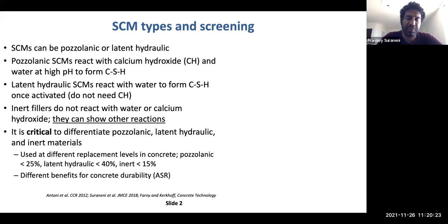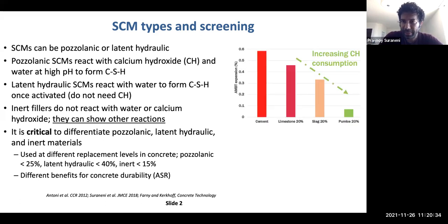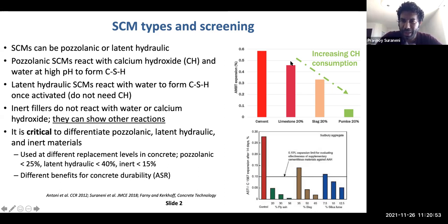It's also critical to differentiate these different materials because they have very, very different benefits for concrete durability. I will give an example with alkali silica reaction. So if you look at pumice, which is a very reactive material compared to limestone, at 20% pumice, if you look at expansion in the ASR test, it is about 8 to 10 times lower than the expansion that you get with limestone. Similarly, if you look at the replacement levels needed to mitigate alkali silica reaction, with silica fume, you can actually mitigate it with just about 8%. For fly ash, you need about 20%. And for slag, you need more than 35%. So for different durability issues, the way different SCMs operate is again different.